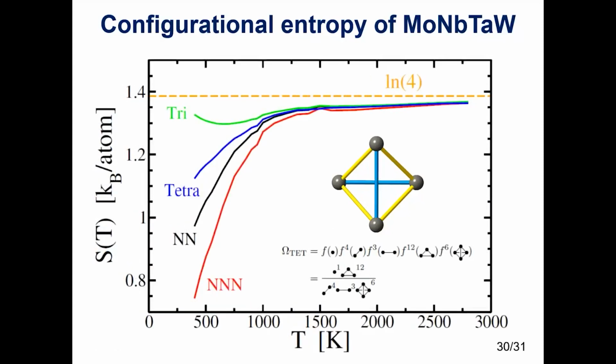And these are the entropies that would be predicted according to the different methods. You see that the entropy reduction due to near neighbors is pretty well captured. The exact entropy is pretty well captured even at the near neighbor level until we pass below that phase transition, at which point we need to use the full tetrahedron entropy to get an accurate result.